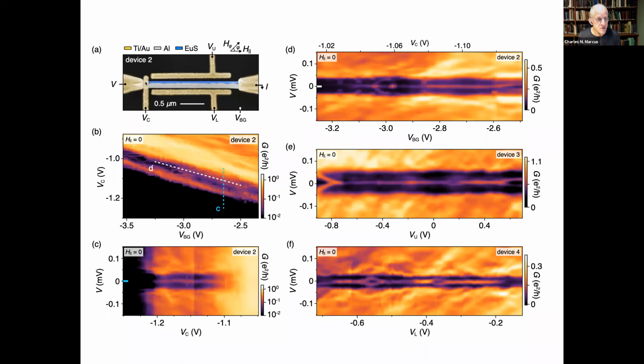And when the gate is across the end of the device, we can tunnel into the semiconductor because you can deplete it. There's no aluminum underneath this gate. There's only semiconductor and europium sulfide. And what one sees experimentally is that you can do a couple of different kinds of curves.